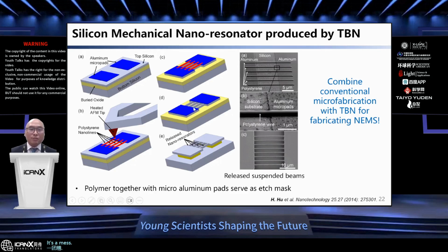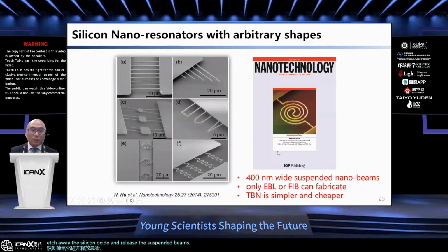Then we do one-step etching of silicon so that both the microstructure and the nanostructure are transferred to the top silicon. Then we just need to etch away the silicon oxide and release the suspended beams. So we can make arbitrary shapes of silicon mechanical nanoresonators. So if you look at this, it's about 400 nanometers wide.